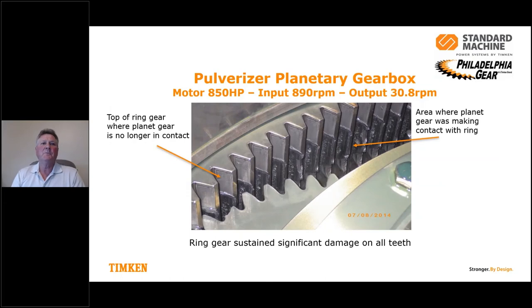The next thing we did was we looked at this ring gear, and we noticed that the top part of the ring gear, where the planet gear should be in contact, was a lot less damaged. So there was some wear there, so it initially did have some contact. But as the damage progressed, we noticed that because it had moved up, there basically was very little contact anymore by the time it failed. And the damage to the ring gear was significant.